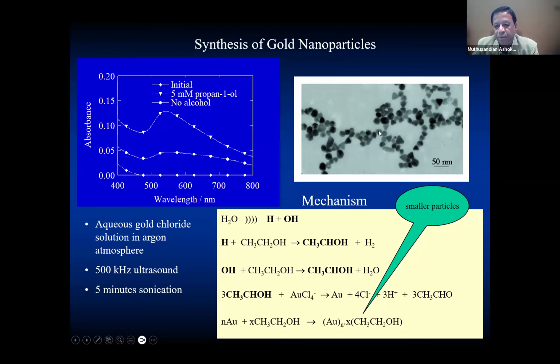The electron microscopy picture that you see here shows that the particles that we produce are anywhere between 20 to 50 nanometers, and they have different shapes. Some of them are cylindrical, some of them are triangular, some of them are spherical, and so on. Later on, I will highlight how to control the shape and size of the particles.